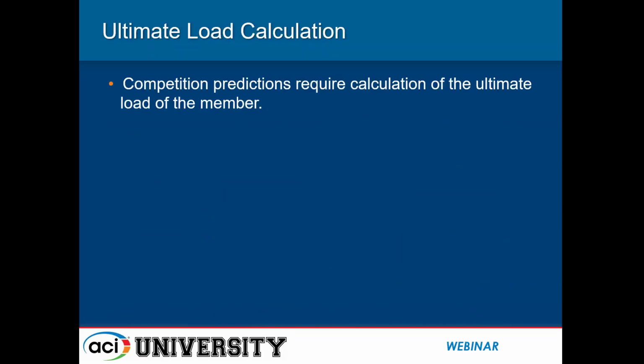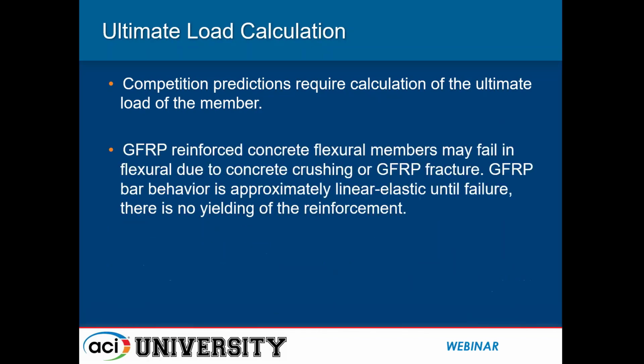For ultimate load calculation, you are required, again, for the predictions to predict the ultimate load of the member. And GFRP reinforced concrete flexural members may fail in flexure due to either concrete crushing or GFRP fracture. GFRP bar behavior is approximately linear elastic until failure, so there is no yielding of the reinforcement.